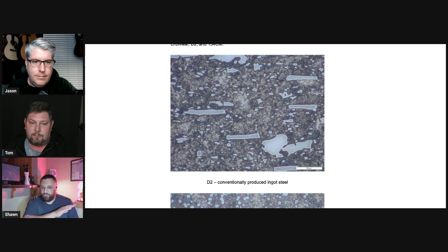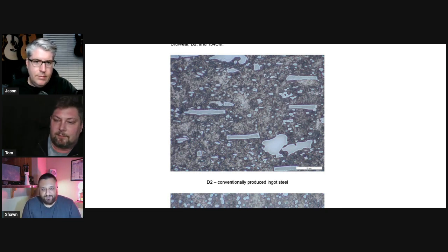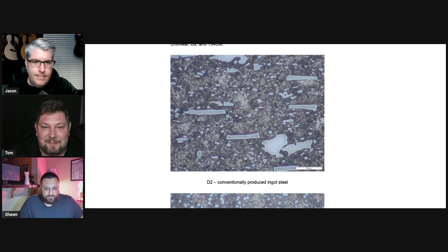They're harder. They'll last longer when it comes to wearing and rubbing on the surface. But if we put shock load on that, it's easier for the cracks to connect between the carbides to break, and then cracks through the matrix to connect between carbides and for it to break out. So those are gigantic carbides. That's why some people may feel like D2 has maybe more edge aggression.